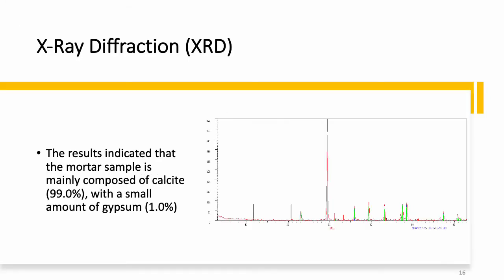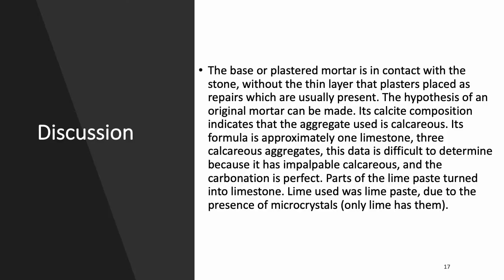In the case of the X-ray diffraction, the results indicated that the mortar sample is mainly composed of calcite, with a small amount of gypsum. The base or plastered mortar is in contact with the stone, without the thin layer that plasters placed as repairs, which are usually present. The hypothesis of an original mortar can be made. Its calcite composition indicates that the aggregate used is calcareous. Its formula is approximately 1 limestone, 3 calcareous aggregates.